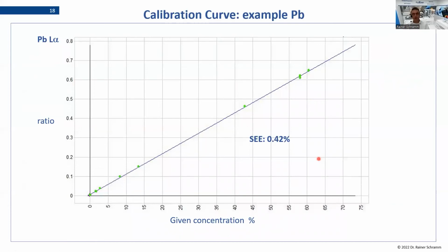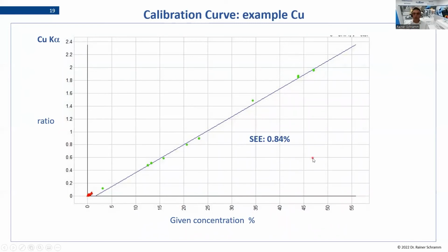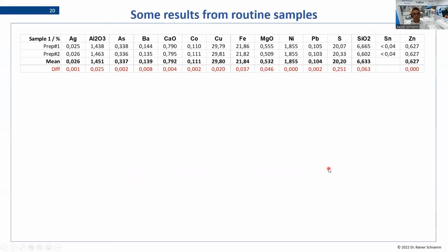Okay, let's see some calibration curves, like for example here for lead. So you see we have here two groups, a high range and a low range. All together would be around 0.42% standard deviation. Of course, in the end, what I would do is, when we go then in the routine analysis, to take this general application and split it into a lead ore, into a copper ore, cobalt ore calibration. So then you can make fine adjustment, split the calibration ranges so that you get even more precise and accurate in these ranges. This, for example, you can see in copper. There we have two groups here on calibration. Altogether has quite a high standard deviation. But for example, if we just take the low side, we are already at 0.15%, and this is what you want in the end.